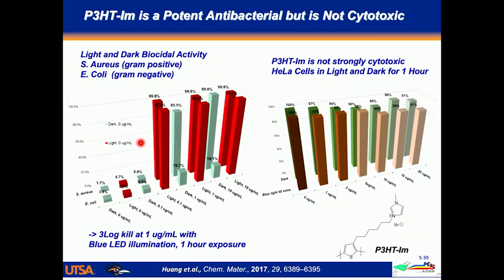So this polymer, again, at 1 microgram with 1 hour of light exposure is getting almost 3 logs of kill of bacteria. Just to give you a calibration, a common antibiotic like ampicillin, to get this kind of killing effectiveness in an hour, you'd have to be at about 100 micrograms per milliliter.